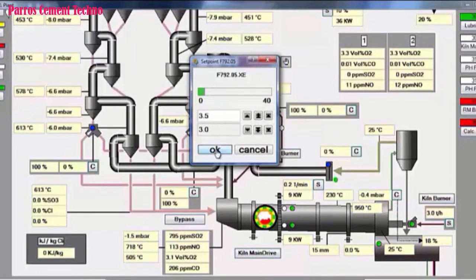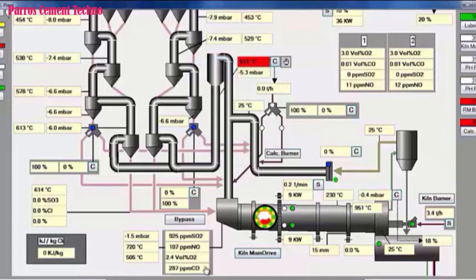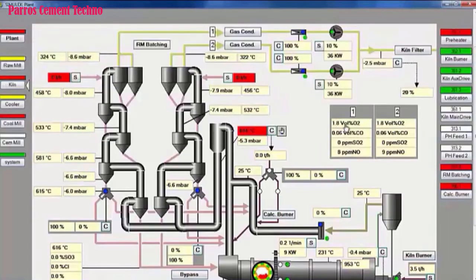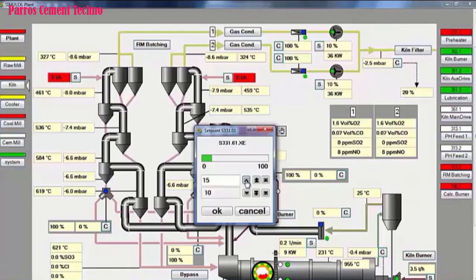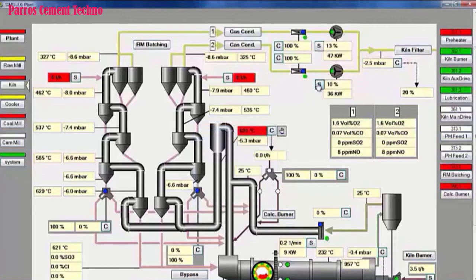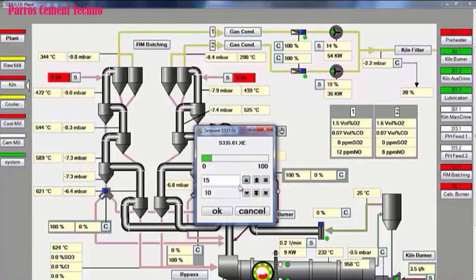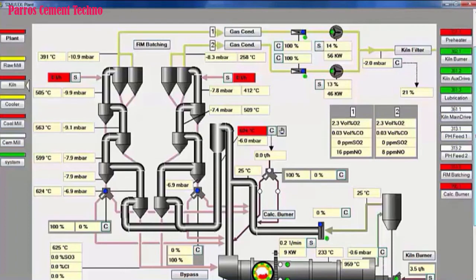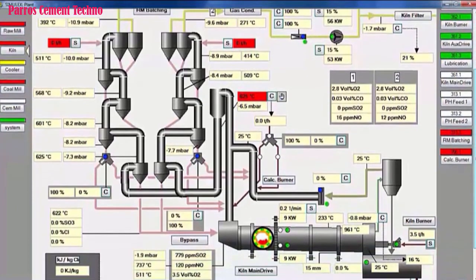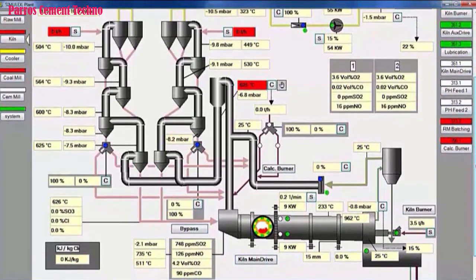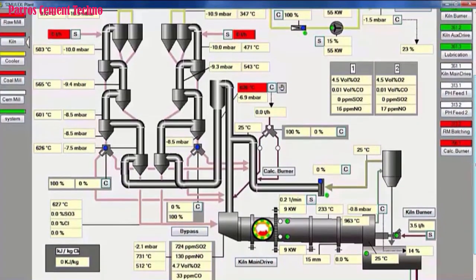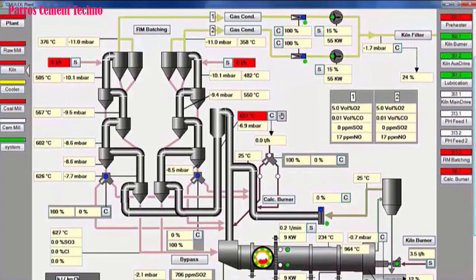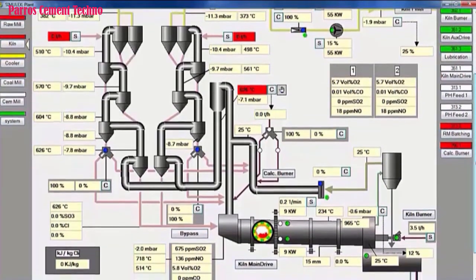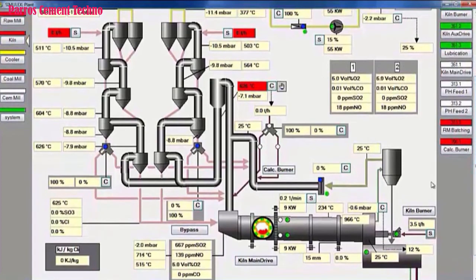per hour. We observe the process, then here O2 is low and CO starts to rise, so we increase the preheater ID fan speed from 10% to 15% for line 1 and line 2, so that CO does not continue to rise, both in the top preheater and in the kiln inlet. CO has started to tend to fall and O2 in the preheater has started to rise above 4%, and also at the kiln inlet. So, when we are ready to feed, we just need to increase the fuel and start